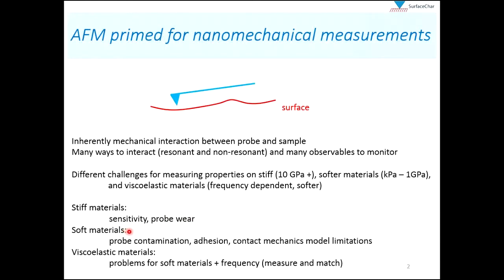Now in soft materials, AFM faces different challenges. So now probe contamination can be a problem. A lot of soft materials can be fairly sticky, so adhesion is a challenge. And finally, limitations in contact mechanics models that are available to us to model the interactions between AFM tip and samples, they have limitations and they don't always work for all the samples, all the materials that one might want to measure.